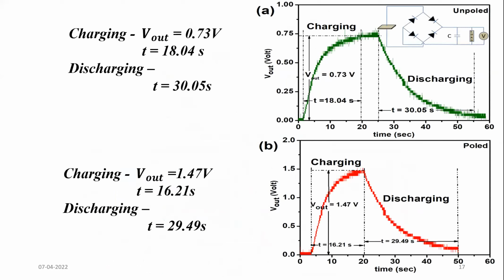Now this is the final DSO result of poled and unpoled film. The charging was for the unpoled film. V output was seen 0.73 volt for charging at time 18.04 second, and the discharging time it took was 30.05 second. For the device which was poled under 15 kV per mm high voltage, the output was seen to be 1.47 volt, which is obviously higher than the unpoled one, and in time 16.21 second, and the discharging time was 29.49 second.